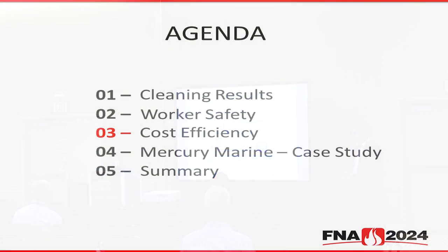So what you would typically do is bring the solvent into vapor phase, and you blow that hot solvent vapor into the cleaning chamber, where the solvent condenses on the parts and rinses off really the last layers of oil that might be there, which gives you the premium or high precision degreasing results. And then afterwards, you dry the chamber, right? Only when the solvent is off the parts, it would open up again and you get out cleaned and dried parts. Good. So, cleaning results, worker safety.